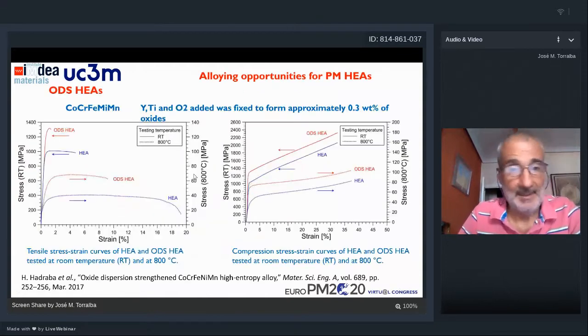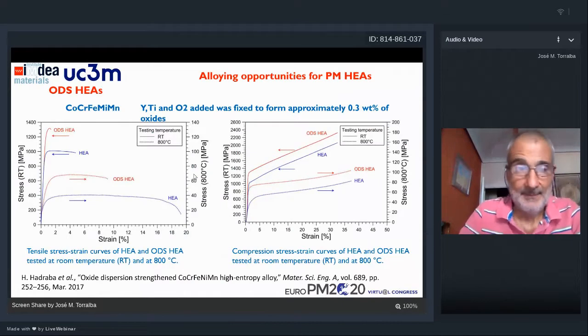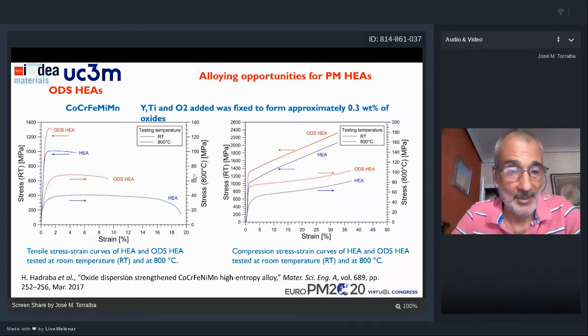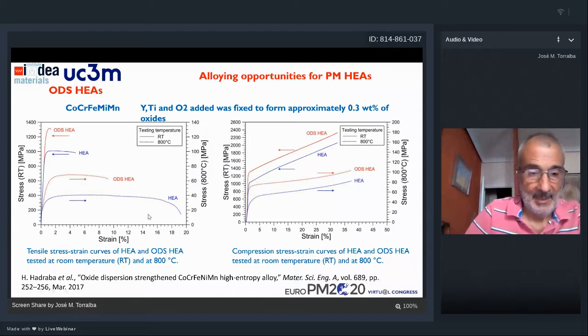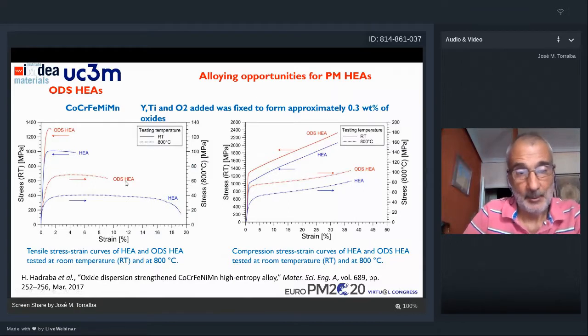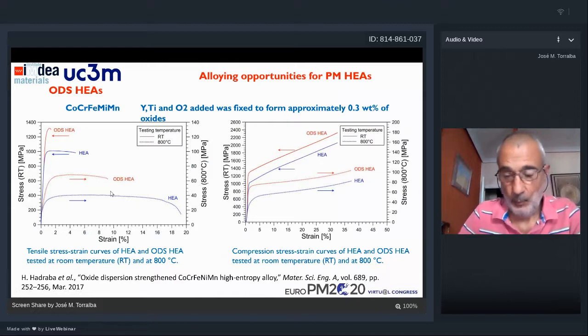Another interesting possibility in the case of the powder metallurgy process is to develop the ODS, oxide dispersion strengthened materials. This is another interesting field, because in this way we can cover high temperature applications. As you see here, we have the high entropy alloy, tested at room temperature and at 800 degrees. And here we have the oxide dispersed high entropy alloy with yttria and titanium oxides. So we see that we improve a lot the stress, the tensile features, without reducing so much, in the case of high temperature, the elongation. So this is another interesting field that could be developed by combining high entropy alloys and powder metallurgy.